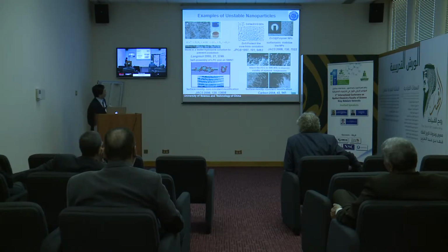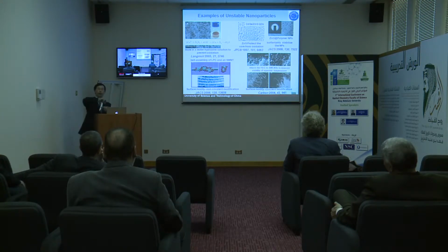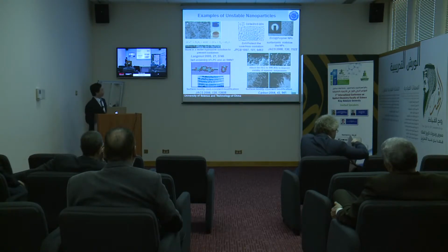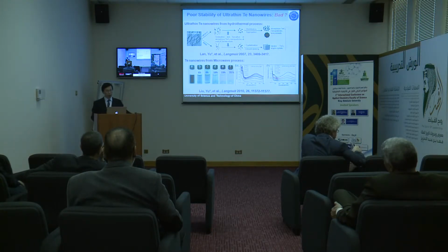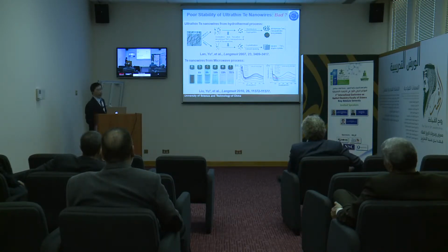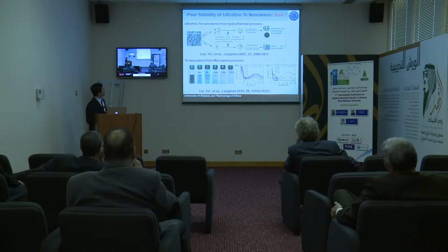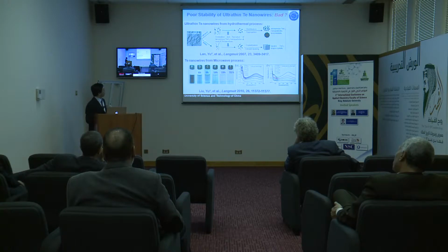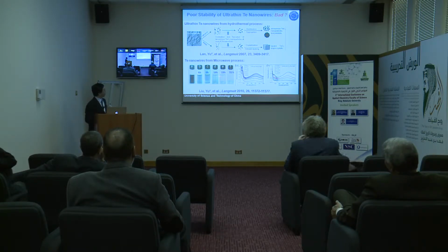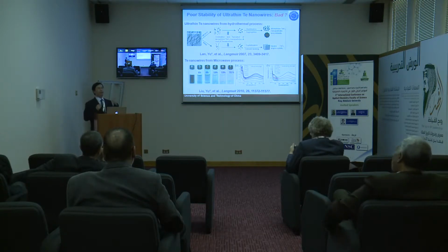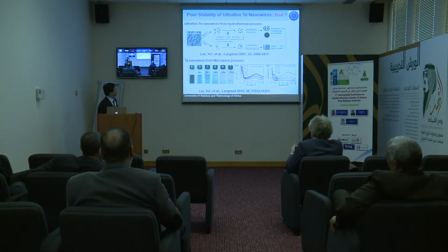For example, copper nanowires are very easy to oxidize even if you store them in a vacuum, if you isolate them from oxygen. A small amount of oxygen can make them oxidize totally. That's the case even for quantum dots. So their stability is a big issue in the future. In my group many years ago, we found that these tellurium nanowires, elemental tellurium nanowires, have very beautiful structures, high aspect ratio, very narrow diameter, but if you store them in ethanol or water solution, a few hours or several days later, they will totally disappear because they are oxidized. These guys are very reactive, right?